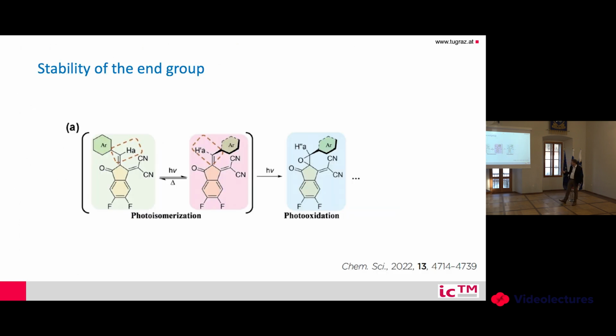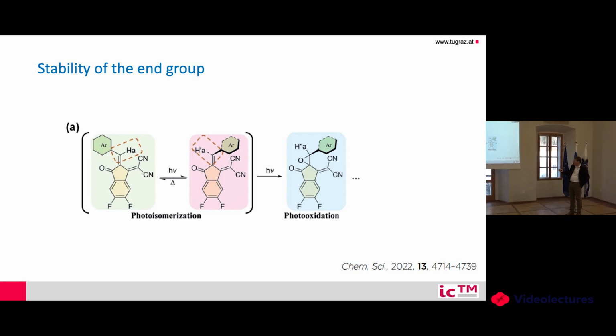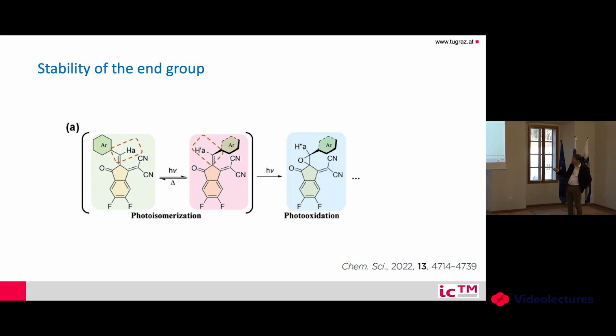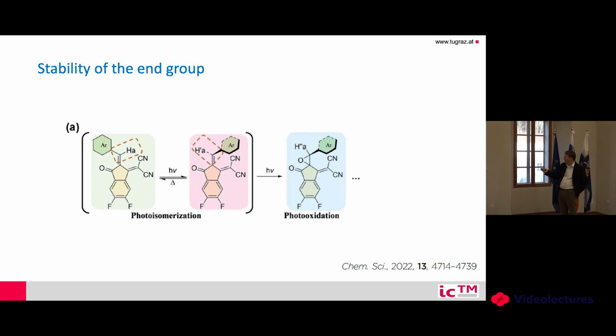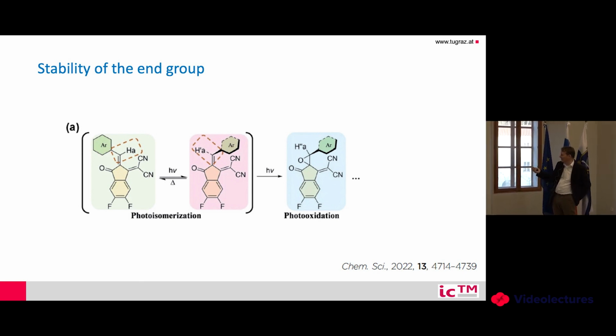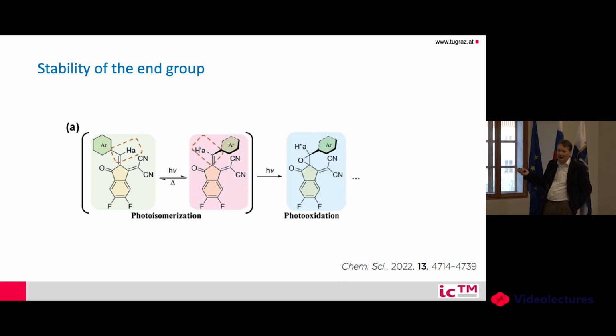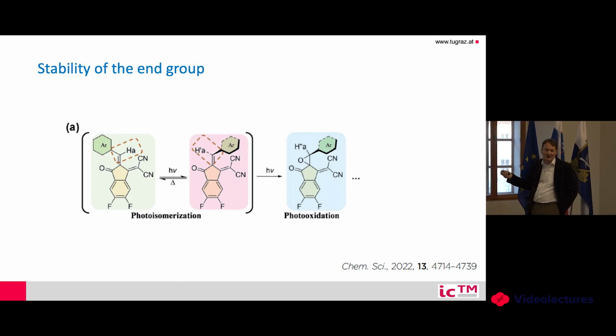Yeah, but actually this group can, under light, photoisomerize, and in this configuration with oxygen they form an oxirane ring and destroy the conjugation, and then destroy the electronic system, because this double bond is of course connected here and you destroy the conjugated system. And you see, of course, one problem is that you really have to exclude oxygen, but nevertheless, also this rotation, there are some other side reactions which can take place.